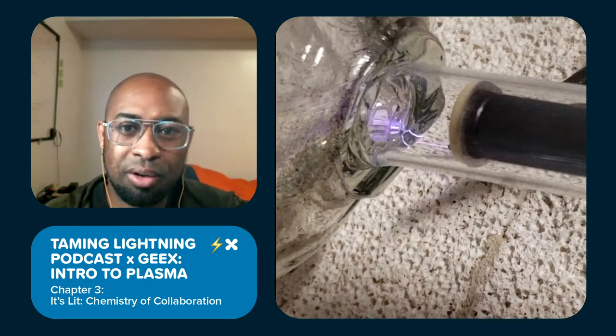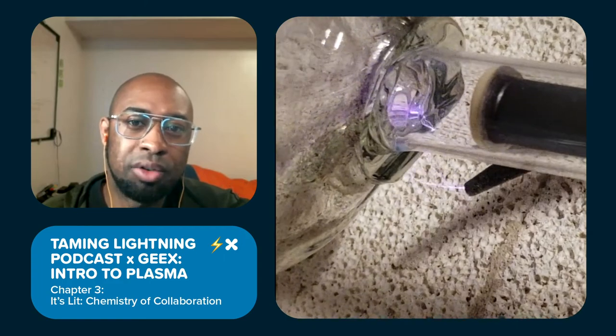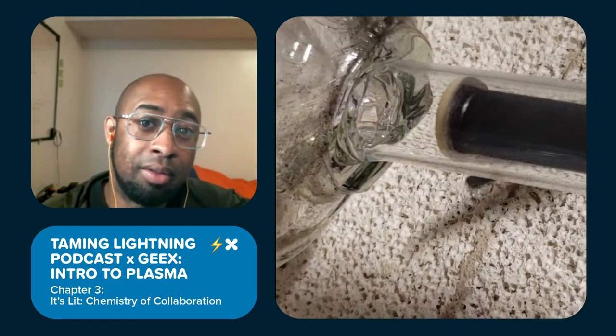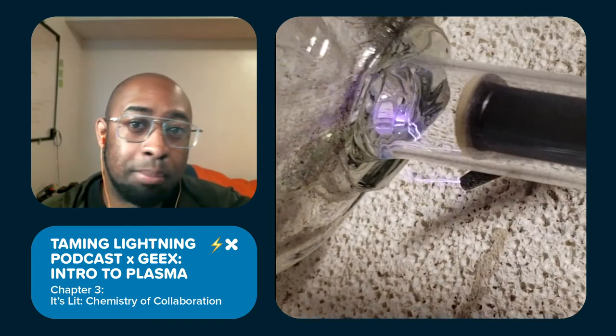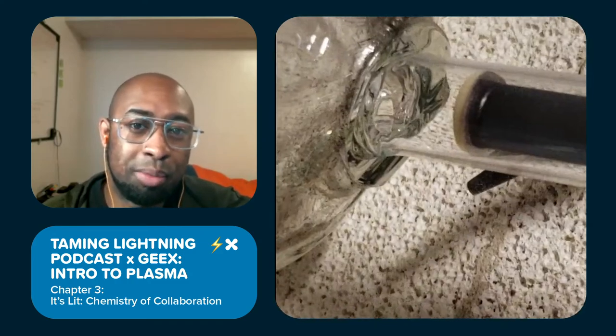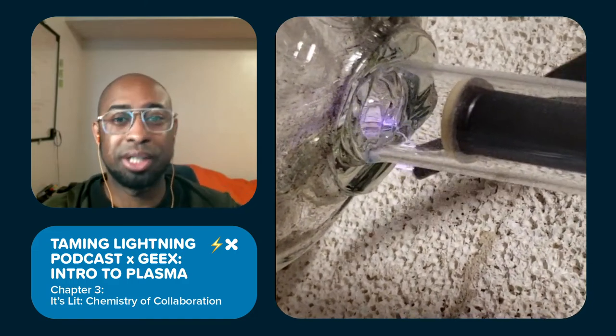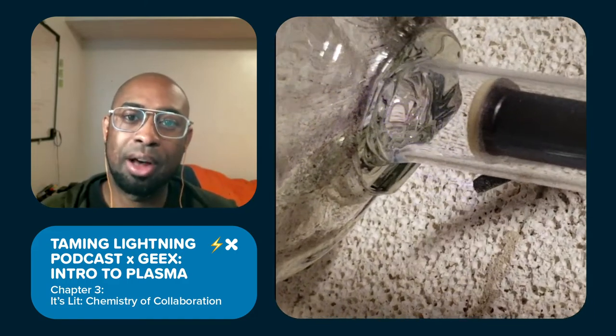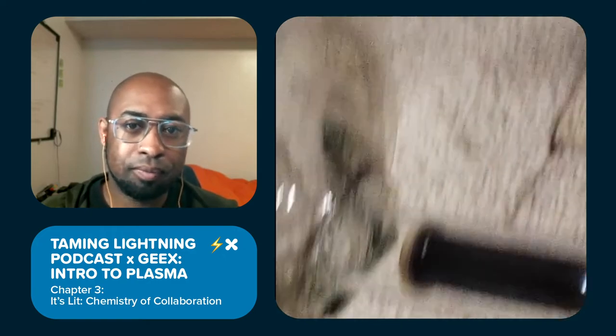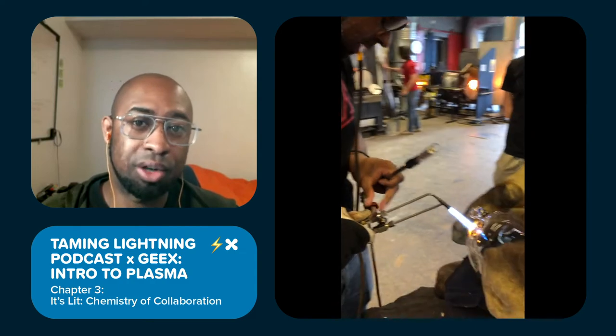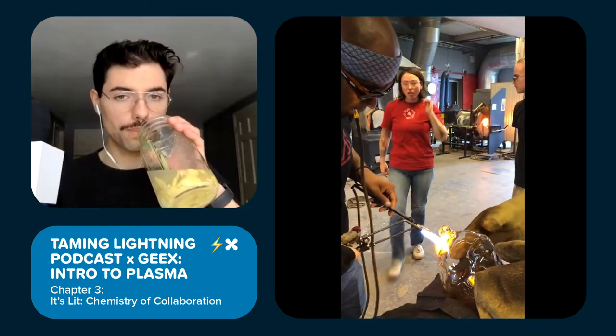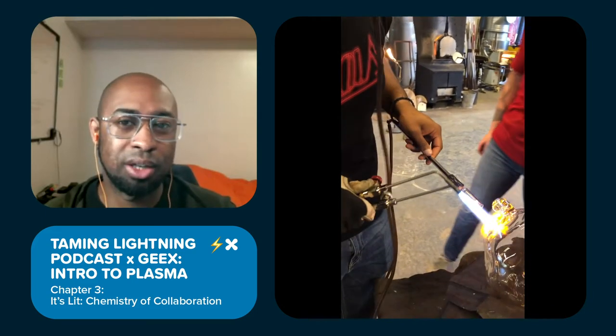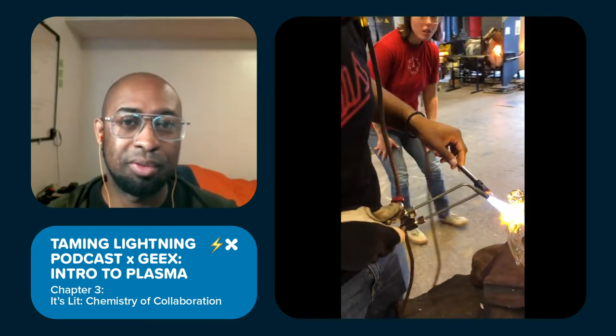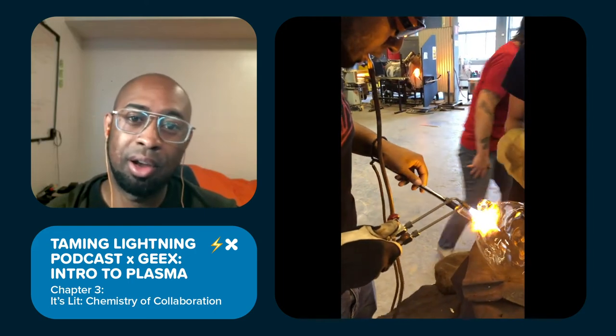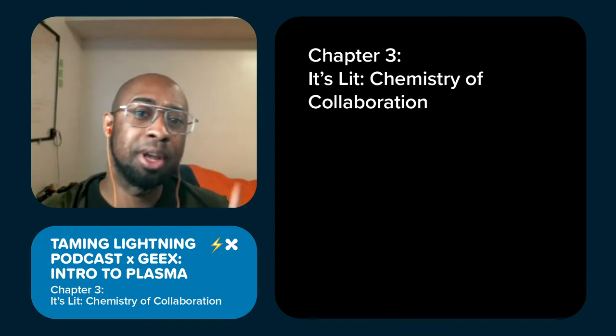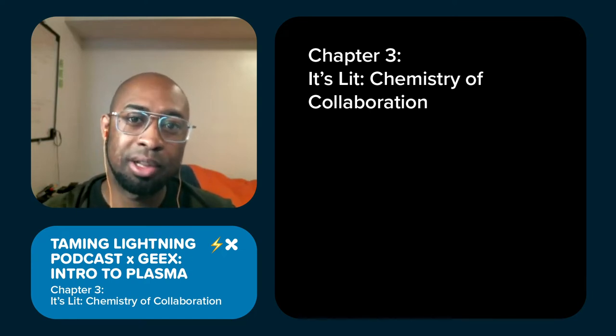If it's a tubulation/electrode weld, you can try to gently reheat the repair and re-anneal the piece. But if you have a direct weld on your electrode to your piece, it's better off starting over. Now, if you want to attempt a recovery, slowly bring the piece up to working temperature in the kiln. Pick it up from the hot kiln and reattach your electrode to tubulation with a direct weld. Note that it does take a lot of time and a lot of coordination with your studio or facility to make this happen smoothly, and you must be familiar with your assistant in order to make this very successful.